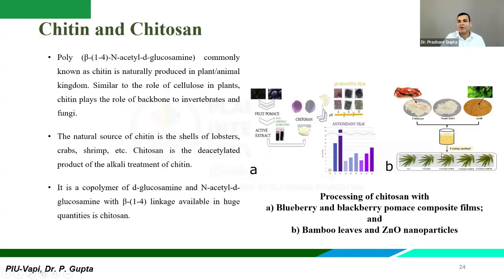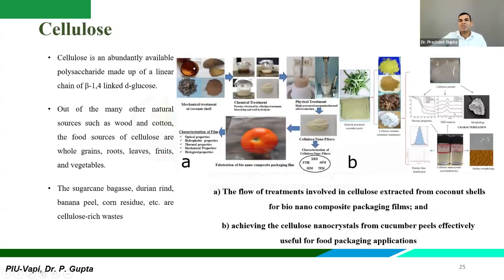But then when the coating is applied on top of it, it certainly changes the appearance a little bit, but not by that amount. So in the same way, cellulose, these are practical research examples. From coconut shell, they are ground or converted into a powder. They are treated chemically, an alkaline based process. They undergo physical treatment and are converted into cellulose nanofibers. They must have done a lot of testing, XRD, FTIR, SEM, TEM, AFM, and they are used to make a nanocomposite film which will save the fruit or a perishable product.